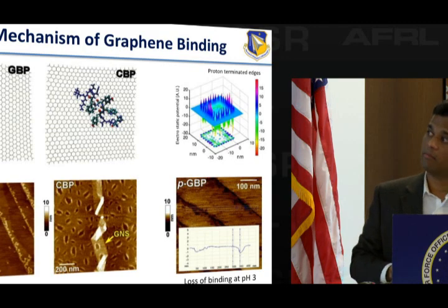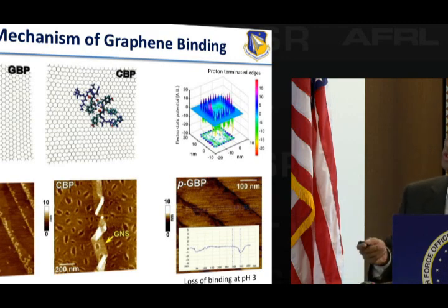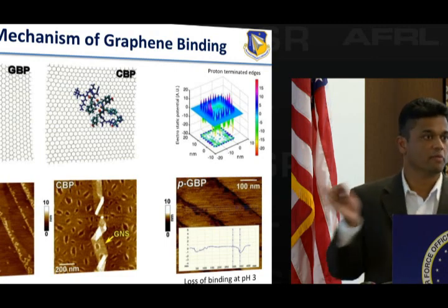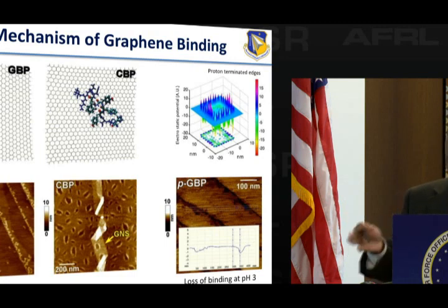So here's one example that we identified. This was published, and it shows that we have a peptide sequence that likes to bind to an edge and one that likes to bind to the plane. Now this is HOPG, highly ordered pyrolytic graphite. That's what we use. We freshly cleave it and use it because we want large areas and you can do AFM and things of that nature.